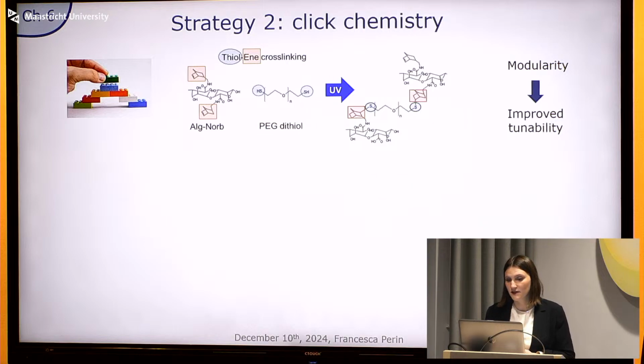And this system had a much higher tunability given by the modularity. So by changing the dithiol crosslinker properties, we could change the final properties of the hydrogel. And it was also very easy to use different peptides for achieving the biological functionalization.